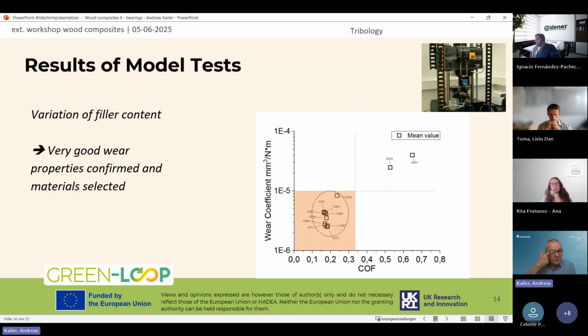And here we have reproduced these tests with a number of trials where we varied slightly the compositions of the materials, always with a biopolymer and different amounts of wood fibers and also different amounts of glass fibers, and in most cases ended up in this very favorable field of very low friction and low wear. So this is very successful. So we have good wear properties and confirmed the low friction values for these selected material compositions.